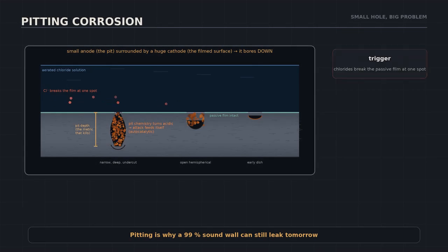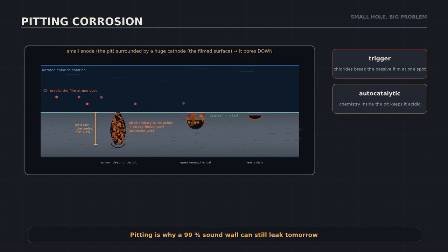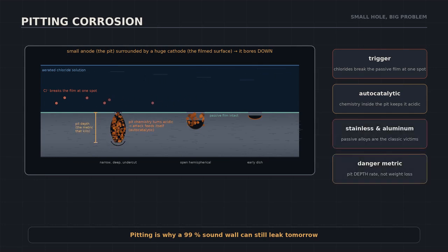Pitting is the opposite, tiny weight loss, catastrophic consequence. It starts when chlorides break down the passive film at one microscopic spot. That spot becomes a small anode surrounded by a huge cathode, so instead of spreading, the attack bores straight down. And it feeds itself, the chemistry inside the pit stays acidic, accelerating the attack, we call it autocatalytic.